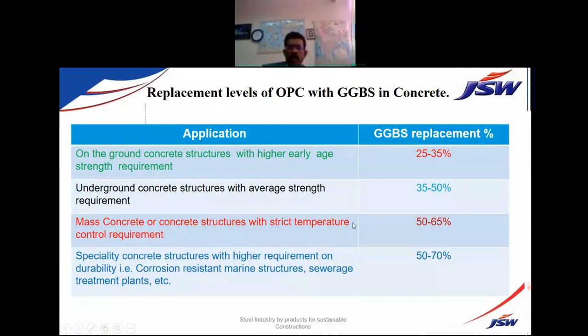Generally, they go with a high percentage of slag to reduce the differential temperature between the top surface and the middle of the concrete, which should not be more than 20 degrees centigrade. So in many raft foundations, you have to control the temperature during the initial stage. They are going with replacement of OPC cement with slag.